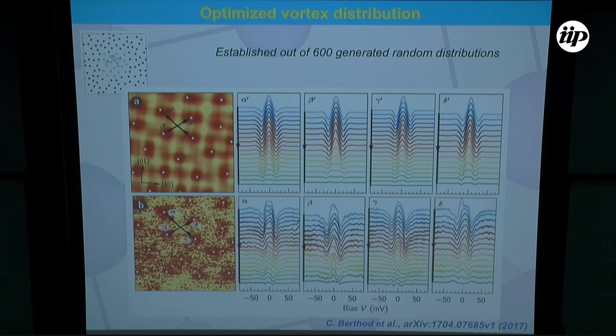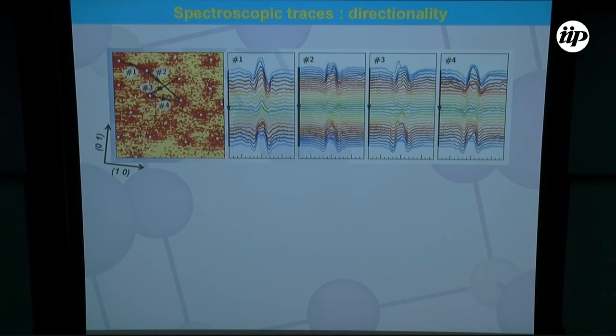So to prove that this is realistic, let's consider other traces. Like for example here, traces 1 and 4, which are going along different crystallographic directions. Compared to traces 2 and 3, which are going along the 1-1 direction of the macroscopic lattice, traces 1 and 4, which are oriented along the 1-0 direction, reveal a small bias anomaly at 0.